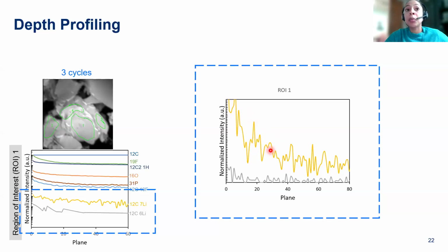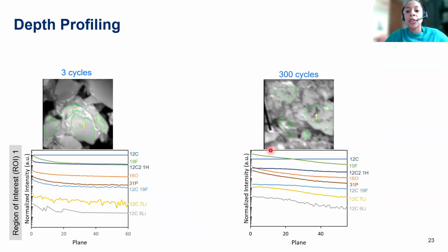Now we can also compare this depth profiling for the low number of cycles to the longer cycles. So we have 300 cycles here, and we can see immediately a much more increased fluorine signal, which corroborates well with the image data and the GIF that I just showed. We also see a much more drastic decrease in the oxygen and phosphorus signal, and just higher signals of lithium as well.